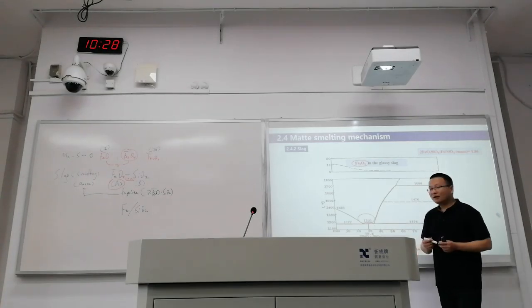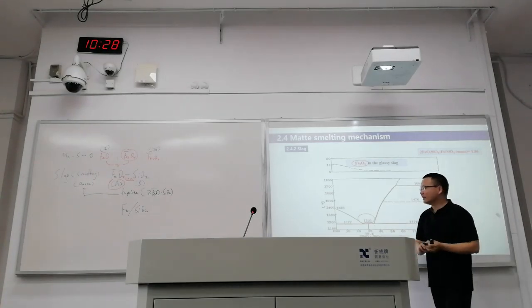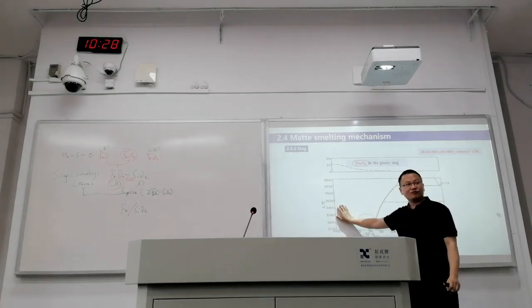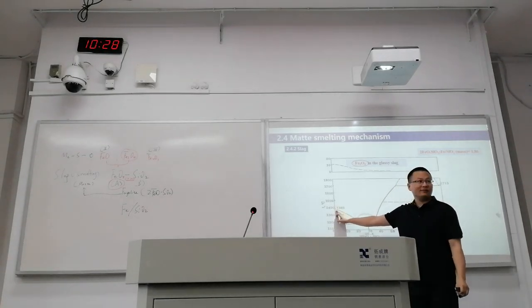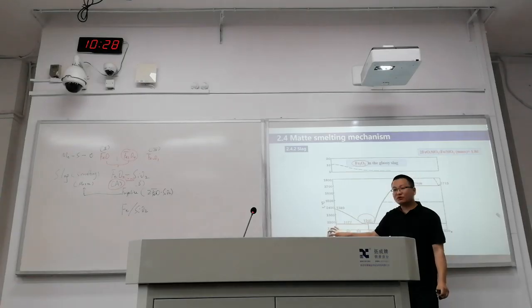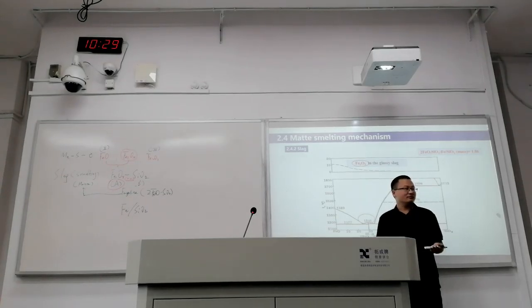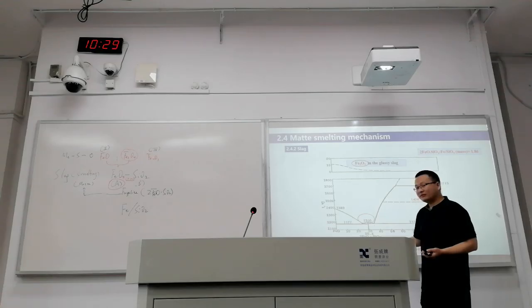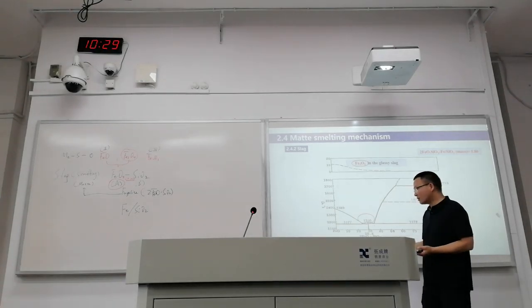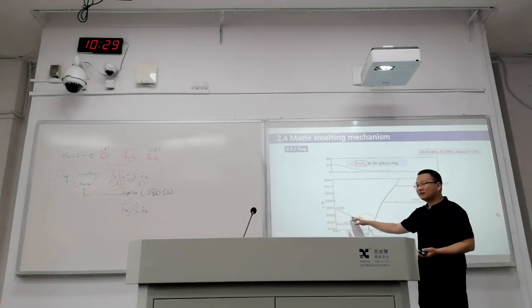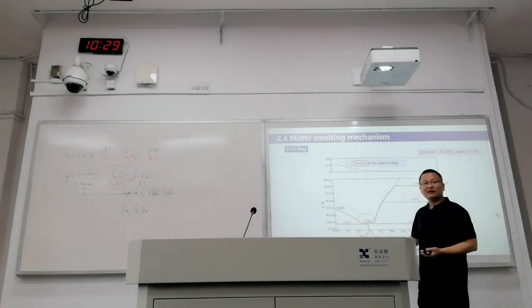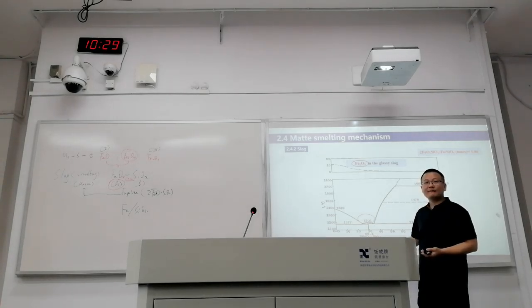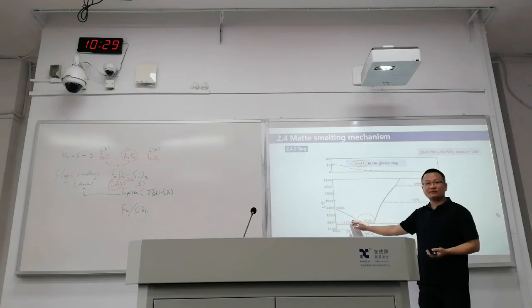Okay. As I mentioned, in the concentrate, after oxidation, the position will be somewhere here. We have a very large amount of iron oxide, very limited amount of silicon oxide. So this is the starting phase. And if we are adding flux in the form of silicon oxide, we are decreasing the iron to silicon ratio, right? So we are having lower temperatures.